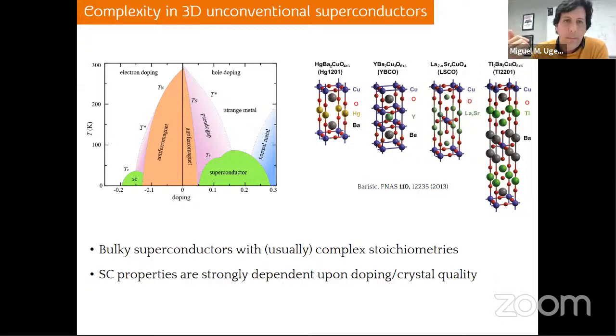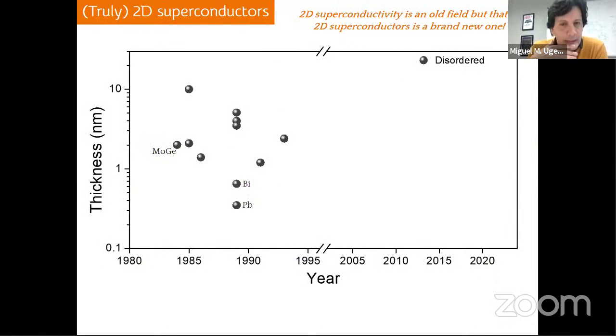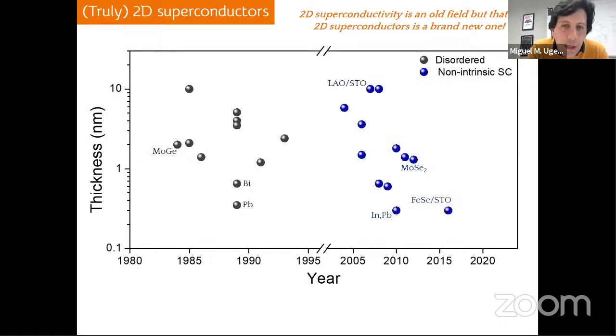So one alternative to these bulky unconventional superconductors would be two-dimensional superconductors, but here we have faced a problem historically. So here you have the evolution of what has been called two-dimensional superconductors. Back in the 80s and the 90s, the best approximation to two-dimensional superconductors were, in general, disordered thin layers of elemental materials like bismuth, lead, or even other materials, but with a very easy stoichiometry. But things changed like 20 years ago or so with the emergence of new two-dimensional superconductors. Here I show you some of them. So it was possible to grow crystalline layers of lead, indium on a particular substrate, or, for example, to grow monolayers of iron selenide on STO.